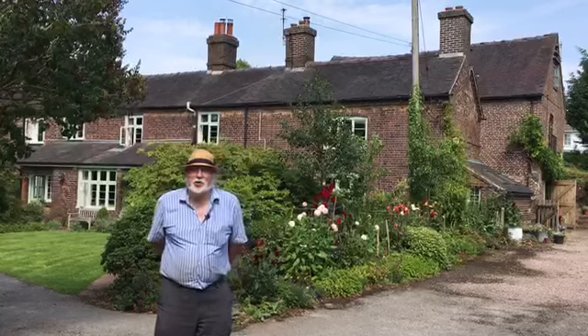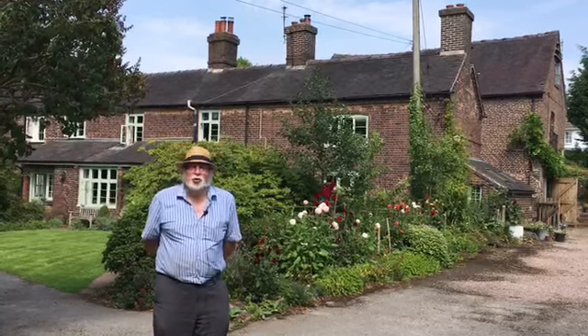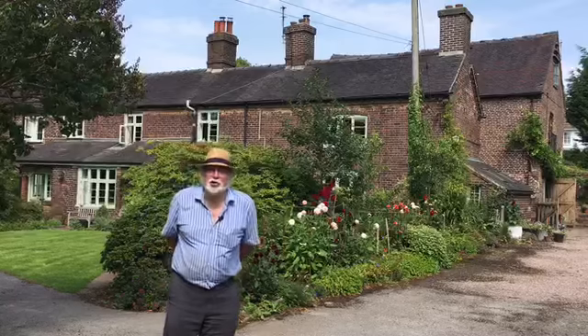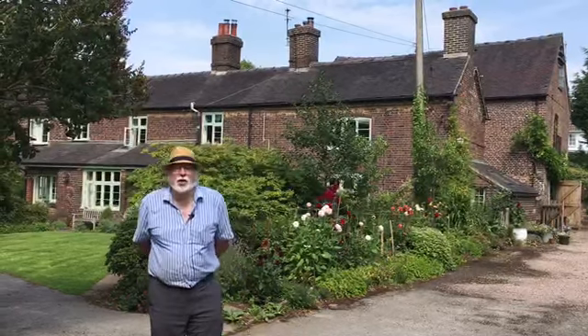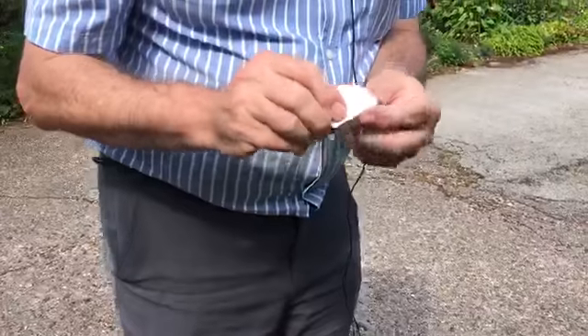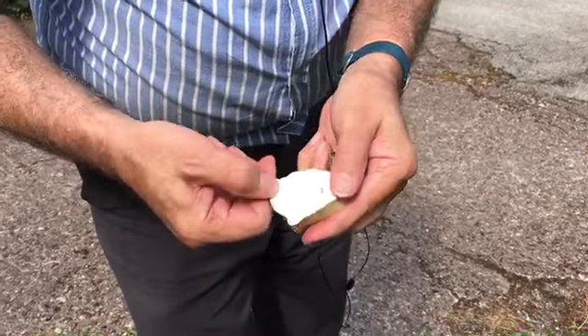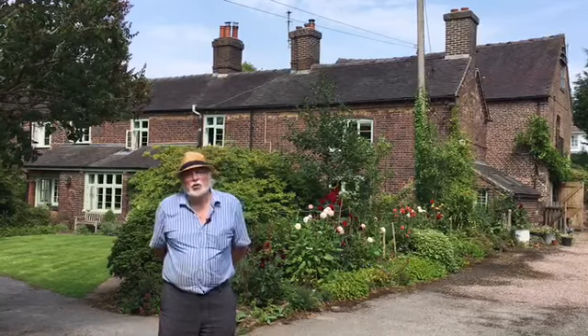If you try and make it into a powder by pounding it, you get a mist of incredibly dangerous razor sharp particles, and originally people tried to grind it by doing it that way. But there was an early patent where the flint was calcined first, which changes the crystal structure and makes it friable, and then it was ground underwater, so there was no dust raised, and then it could be filtered off and used in the pot banks.